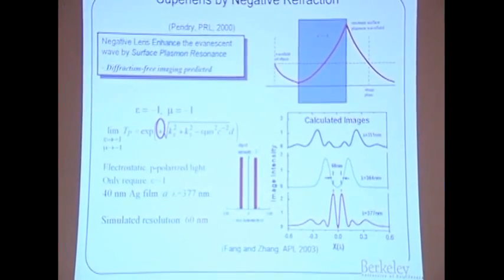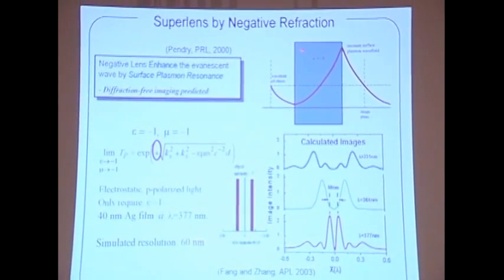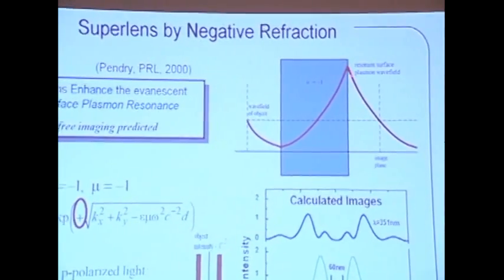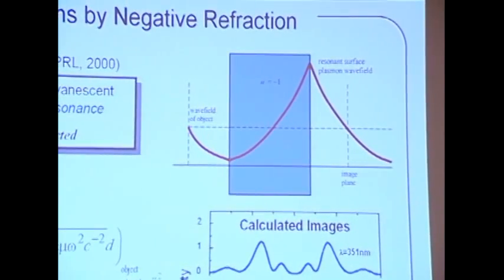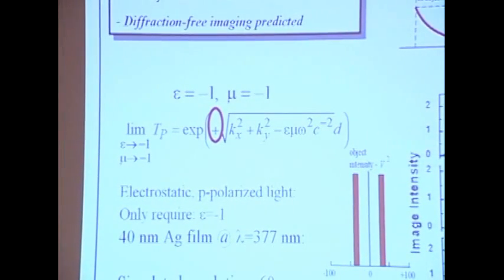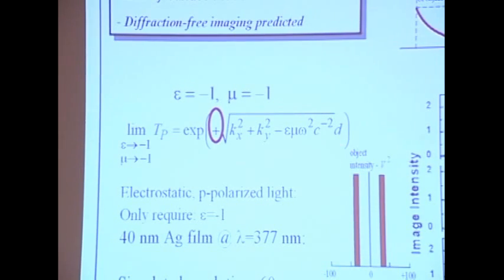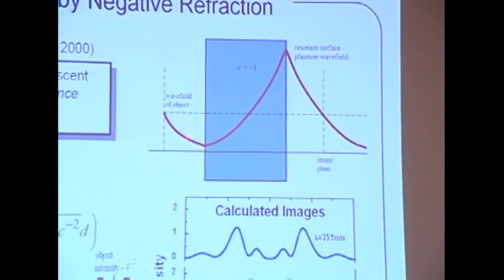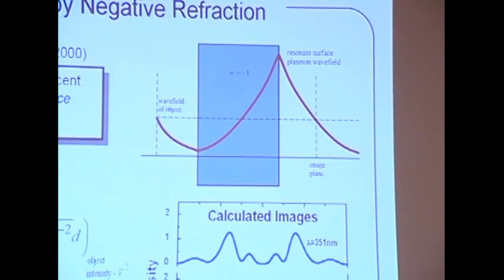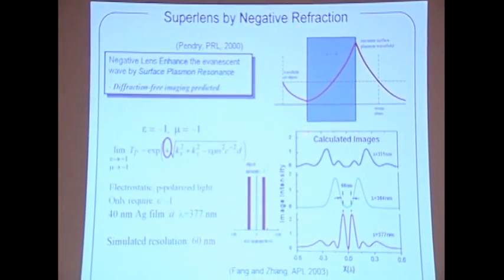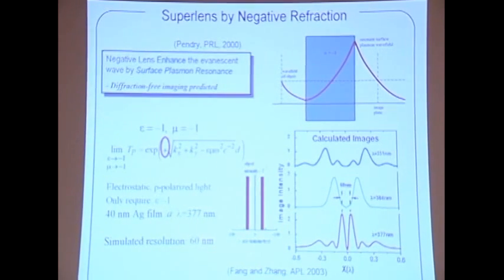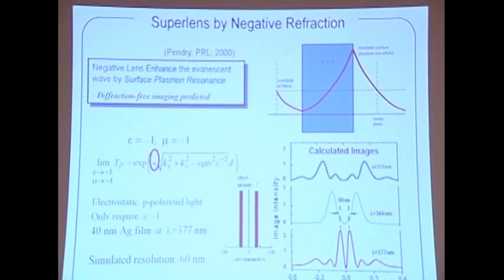cutoff. So what this negative index medium gave, theoretically at the time, 7 years ago, is a possibility that if you plug in epsilon and mu negative and you calculate the transmission coefficient, essentially the field ratio after this medium and before it, that can grow exponentially over this medium with the thickness of the medium. And that is very interesting because it gives you the hope that this growth or enhancement can compensate the decay in real space or positive media. So in the negative medium, the growth could counter this. But actually, as Pendry described, the physics is that you excite surface resonance that establishes the field, which is growing rather than decaying.